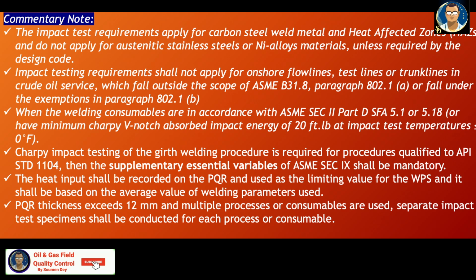Then also the supplementary essential variable for section 9 will now be mandatory. So heat input shall be recorded on the PQR and used as a limiting value for the WPS, and it shall be based on the average value of welding parameters used. If PQR thickness exceeds 12 mm and multiple processes or consumables are used, separate impact test specimens shall be conducted for each process or consumable.